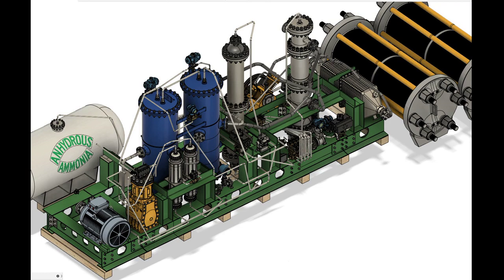translating into roughly 0.28 kilowatt-hours per kilogram of synthesis gas. In traditional ammonia plants, the hydrogen exits the steam reformer at up to 5 megapascal, and while the nitrogen produced from cryogenic distillation can in theory be compressed for free, since the liquid gas can be evaporated in a confined chamber, since most of the volume is occupied by hydrogen, at a 3:1 ratio, this cannot be performed feasibly.